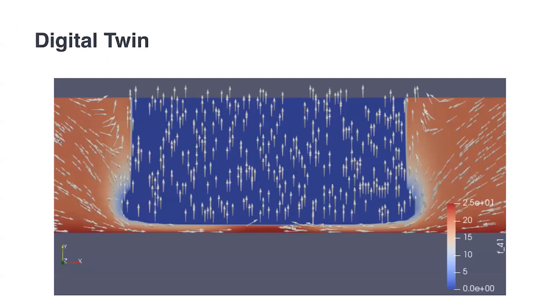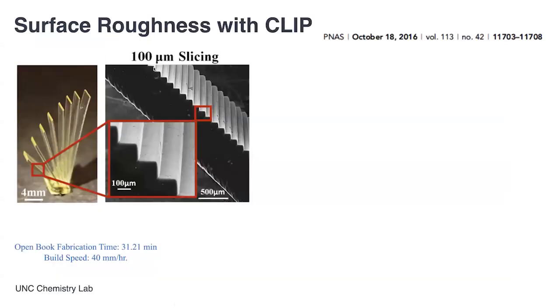So we do a lot of modeling and simulation. This is a really rich and exciting area where you're modeling fluid mechanics, the mechanics of the part, reaction kinetics, and thermal heat evolution. These are exothermic polymerizations. Every 10-degree change in temperature, reaction rates double, and viscosity changes. There's a lot happening, and a digital twin is really critical for monitoring this.